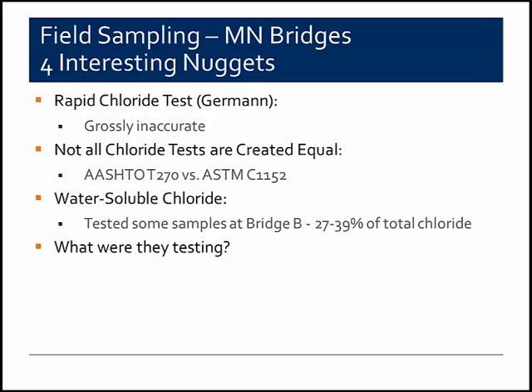So in effect, AASHTO doesn't even like their own test, and it was just something that simply hadn't been checked before the field sampling. And in our opinion, it would have been somewhat significant because, particularly where we were comparing results, the more variability in those results, or that the test procedure leads to variability, it just becomes more challenging to do. If that margin of error is higher, then comparing apples to apples just gets more complicated.